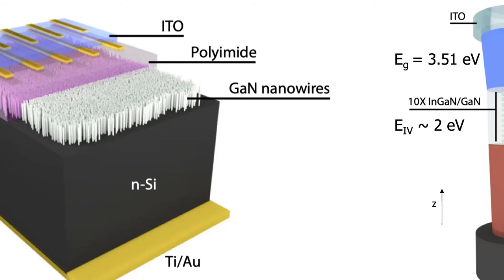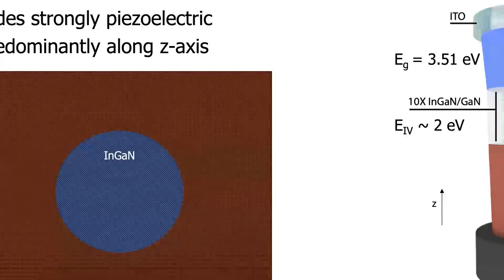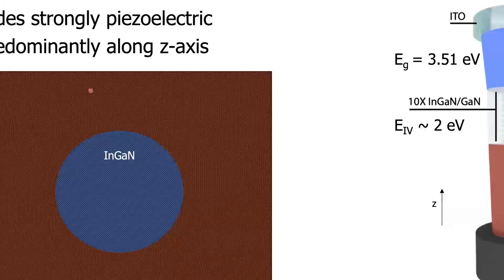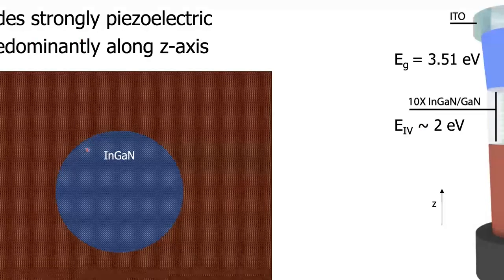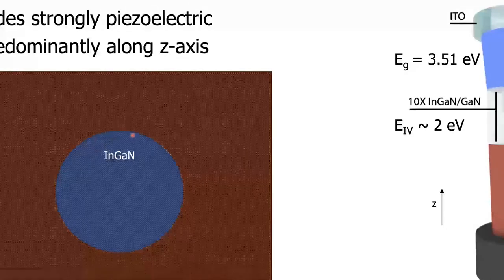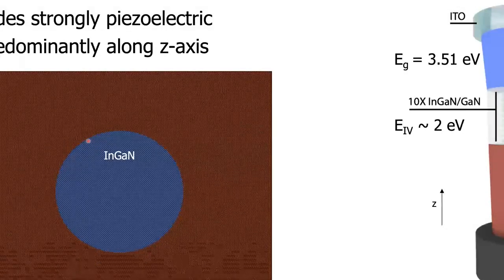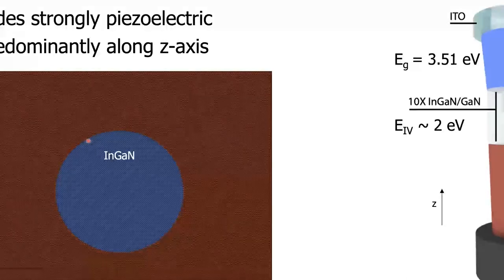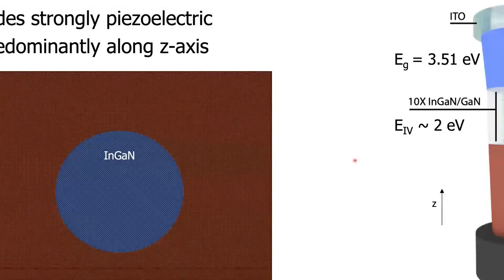They were originally developed to be light emitting diodes, and we are studying to adapt this structure to be a solar cell. One of the interesting things about gallium nitride is that the group 3 nitrides are very strongly piezoelectric. If you can see the dots inside here, what I'm showing is that the indium gallium nitride system has a larger lattice constant than the gallium nitride system does. So there's strain at the boundary, which causes a piezoelectric potential to develop, which is predominantly oriented in this case along the growth axis of these nanowires. I'm going to come back to that in a moment. But first, what I want to do is just show the